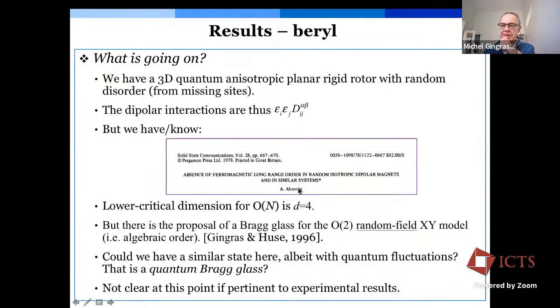And so these interactions would then destroy any possible spontaneously ordered continuous symmetry phases and give rise to a glass phase. This reminds us of the topic of the Bragg glass for the random field XY model, for example, where in less than 3 dimensions there is a speculation that the system would have algebraic order. So when we ask what happens here in the presence of the dipole interactions for these planar rotors, whether or not one has an exotic phase if the fraction of the cages occupied is sufficiently large, the answer to that question is not known.